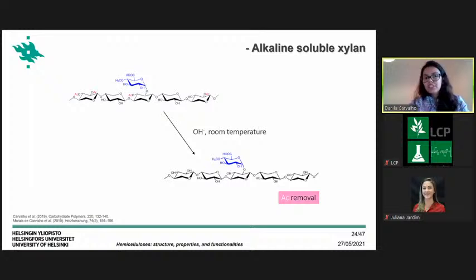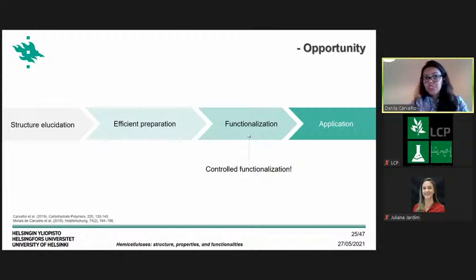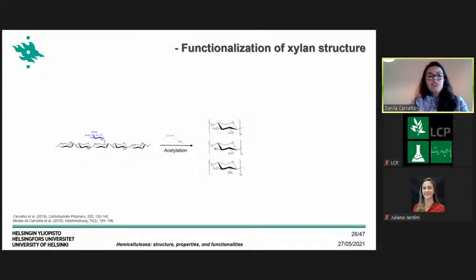And the preservation of acetyl groups can confer some properties to the xylan. So what could be here a limitation, we took as an opportunity to control the functionalization. And what we did was to perform acetylation of the hemicellulose, or the xylan, that we just got without the acetyl groups. And the good thing of this controlled functionalization is that we can get different degrees of acetylation as we want, and also degrees of acetylation even higher than that naturally can occur in the plant.